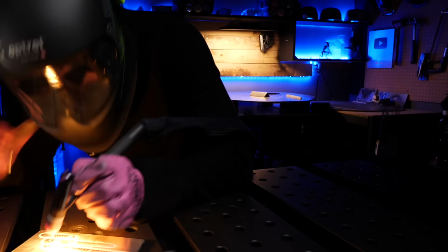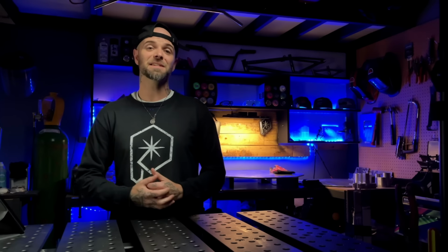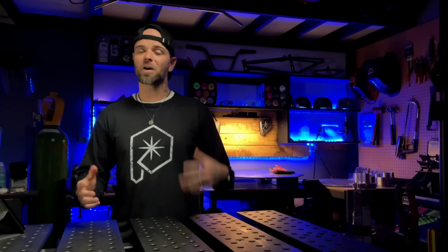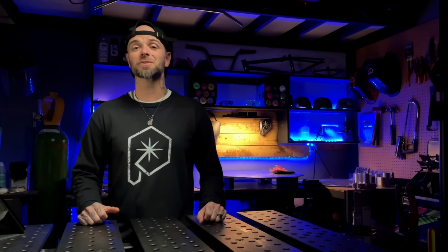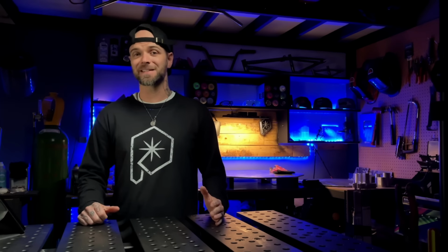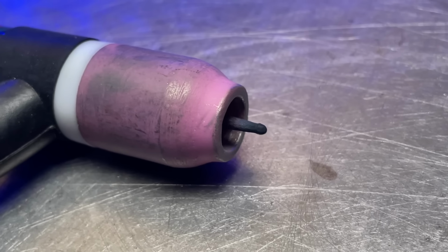You see that? You see how the torch was pulled away from the welding area right after the weld is finished. So even though we have a great amount of time set on our timer, we have good gas coming out of the torch, when you move your torch aside like this, you remove it from the gas envelope and you compromise the consistency of your gas flow severely. To be honest, when I'm filming and I'm watching footage of myself welding, I realize I do this pretty often, but I am trying to improve at it. Obviously, when we do this, our gas flow is going to be interrupted or become inconsistent, and again, that oxide is going to form on our tungsten.